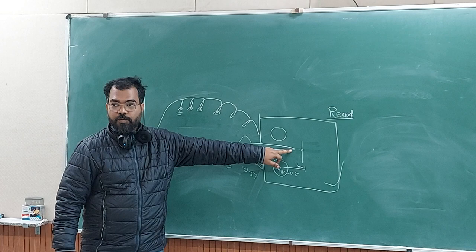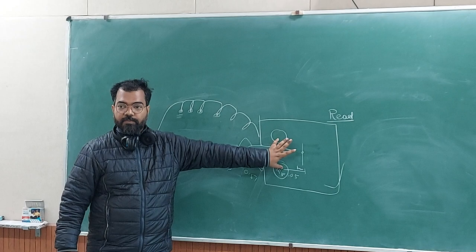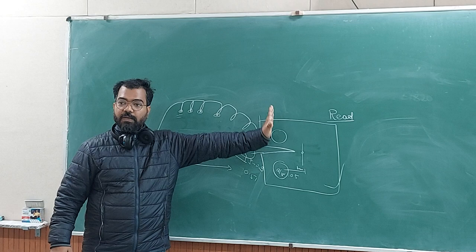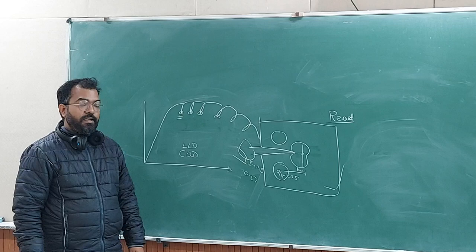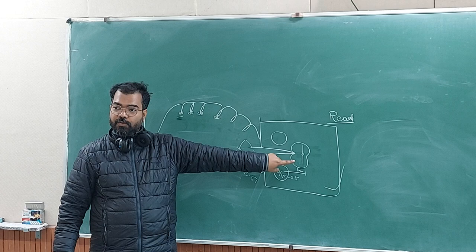Okay, but these holes are not deforming plastically. So on this region, you don't have plastic deformation happening because you don't have that much force here. Your plastic zone is somewhere here, right? So all the other things are not deforming plastically. Okay, so the displacement for the same amount of force which is happening elastically is going to be different from what you will have at the crack tip. So COD and LLD will have differences.